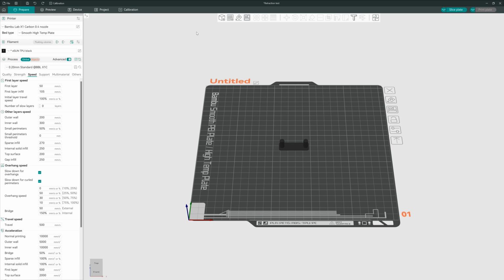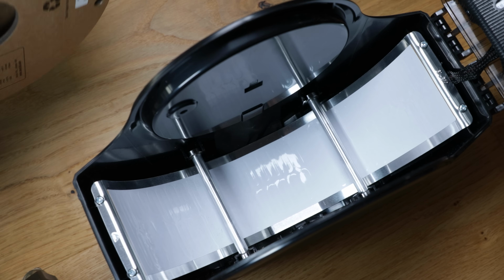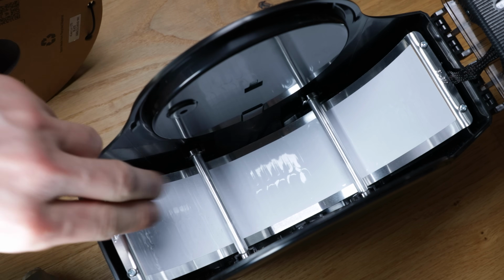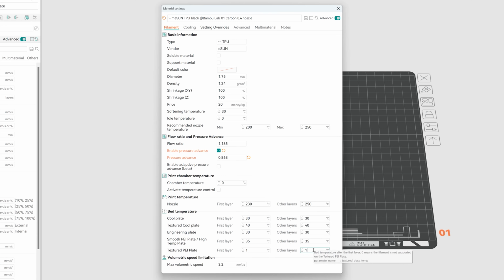That's it. For the sake of completeness, there are more calibration methods, but for this filament I would personally stop here. Let's sum up what we have done so far. Printing directly out of the filament dryer where the spool sits on ball bearings. Heatbed plate temperature lowered to 1 degree Celsius since the parts adhere extremely well without heating. No glue, just the bare plate.